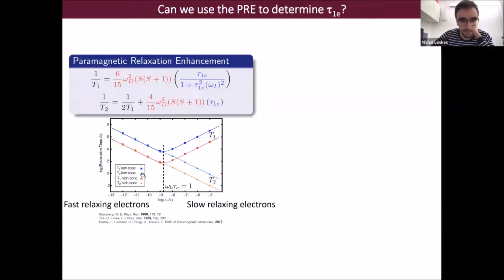we get the well-known BPP figures, where T1 passes through a minimum and then grows, while T2 keeps decreasing with increasing correlation time. And now here the blue and red curves are the same equations with two different dipole coupling strengths. So the red one has stronger dipole coupling. And if we look at these two curves carefully, what we observe is that for a given correlation time, the ratio between T1 and T2 is completely independent of the strength of the dipole coupling, the strength of the interaction. It only depends on the correlation time.